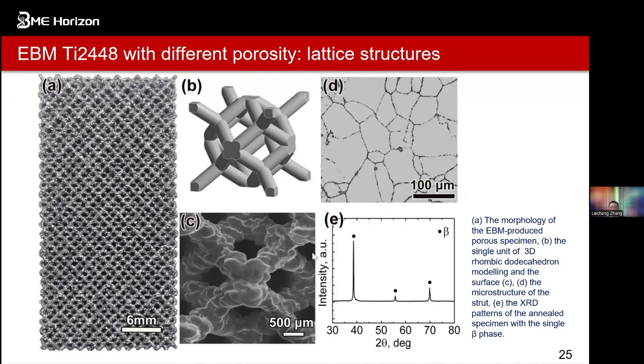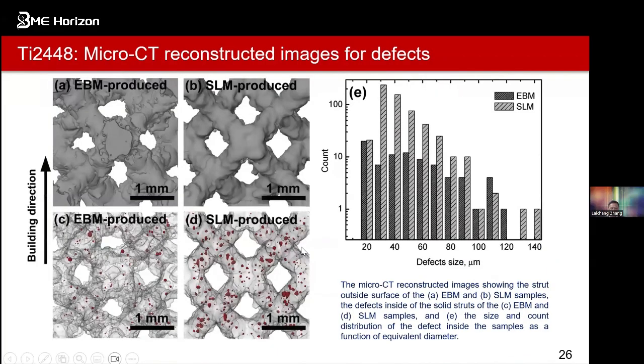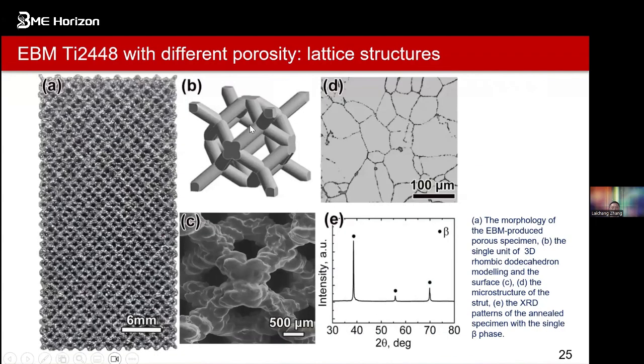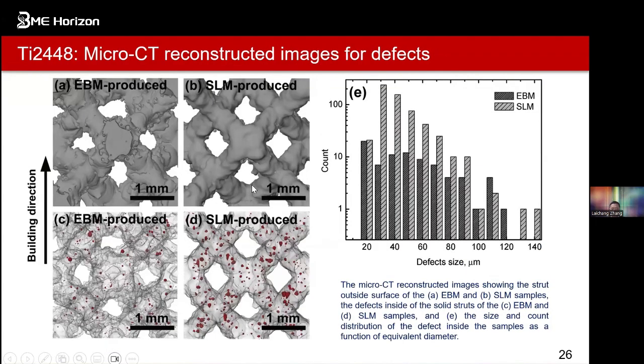So of course, from here, we can see we try to make this one out of beta titanium. And we can compare the two popular methods, one is electron beam melting, we call EBM, and another one, selective laser melting, we call SLM. You will see the surface will be different. The micro-CT image of the single unit cell used for the EBM or SLM shows these things are much different in comparison for this kind of structure. It's apparent that the SLM part has a smoother strut surface than the EBM one. Especially you can see it's much smoother.